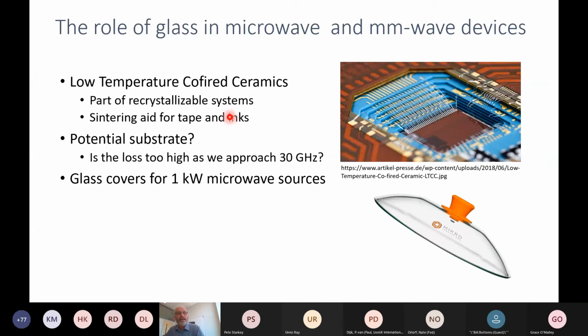So it's very common in low temperature co-fired ceramics to have some sort of crystallizable ceramic from a glass phase to a crystalline phase, or there's a little bit of a sintering aid of the glass that's put into these sorts of tapes that are made for packages. And so glass is a pretty important component for a lot of applications. It could be a potential substrate in itself as we move to new ideas in 5G. Of course, at home, you might have some sort of protection for your microwave oven, so glass is used there as well. So it's an important material to study.